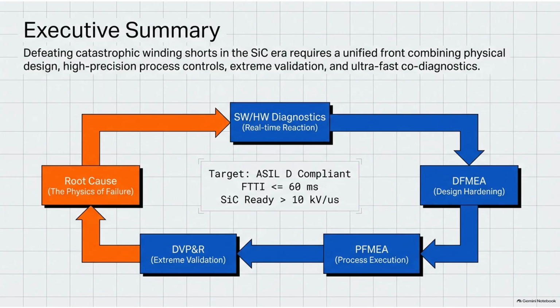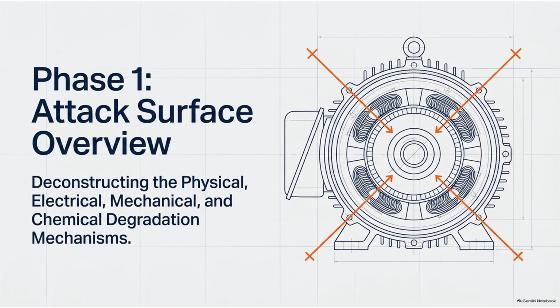That sets us up for the second factor, which frankly sounds like a localized thunderstorm inside the motor. It really does. Partial discharge caused by silicon carbide or SiC components. Now, silicon carbide is the darling of the modern EV world because it's so efficient. But that efficiency comes with a massive penalty, doesn't it? It does. I mean, silicon carbide power modules allow us to reduce switching losses because they can turn on and off at blistering speeds compared to traditional silicon IGBTs. Right. But that high-frequency switching creates an extreme rate of voltage rise over time, which engineers denote as dV/dt. We are talking about voltage spikes exceeding 10 kilovolts per microsecond.